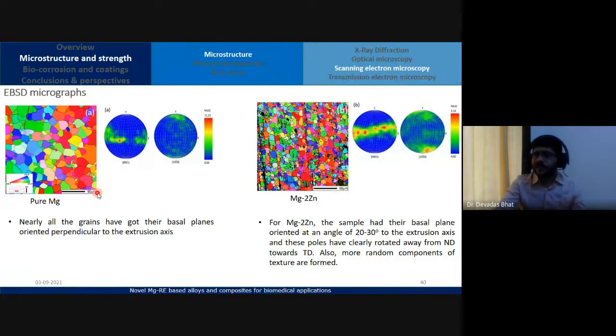To get such beautiful images, we had to polish more precisely, going up to, let's say, 1 micron or even 0.5 micron diamond paste, and then we used ion milling so that we remove the top surface layer. With magnesium, after polishing, when you take it out, in the atmosphere it gets oxidized, right? So we ensure that the sample is always kept in a desiccator under a controlled vacuum.